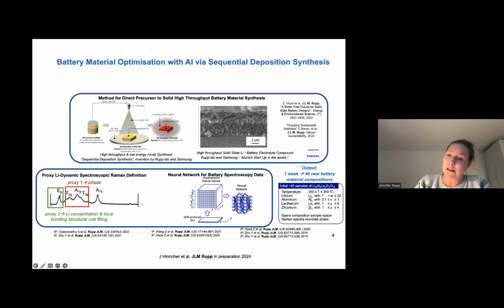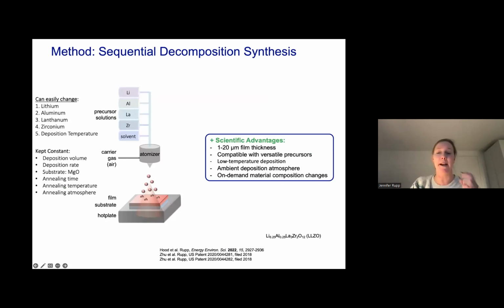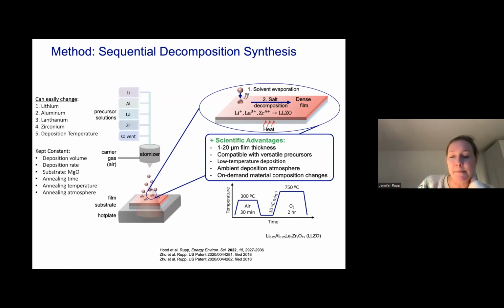So looking now at low temperature, very low carbon dioxide footprint synthesis, we decided to probe the material class and just vary up to 40 samples, really as solidified real materials. And we did that in a week. Yeah, you can make in a week 40 different or more samples, not as a powder, but really as a solidified electrolyte. And you could just say, well, vary for me the lithium, aluminum, lanthanum, zirconium in certain extents, and just change temperature and maybe some other parameters in it. And we can directly see how it impacts. So this is how the experiment looks.